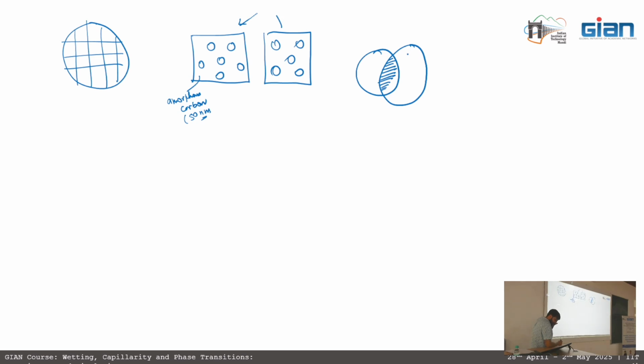One good merit about this case is that once you make these graphene water pockets, you can have multiple experiments, because graphene is impermeable to liquids or gases. Experiments have proven that graphene is impermeable. So once these water pockets are formed, even though the vacuum inside this TEM is 10⁻⁶ pascals, 10⁻⁸ pascals, such low vacuum, ultra low vacuum, even in that case this is stable.